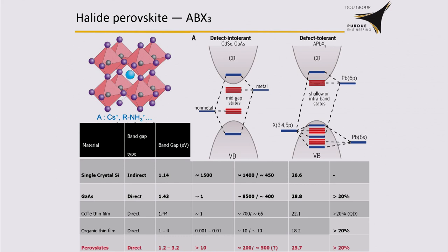Because the crystal polarity is large, it's more like an ionic compound. So lots of the defects are very shallow or even inside the conduction or valence band, making the middle of the gap very clean, so that those defects will not trap the charge carriers and kill the device performance. So that's a very unique feature for halide perovskite material.